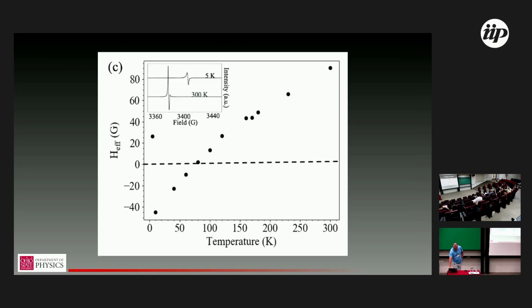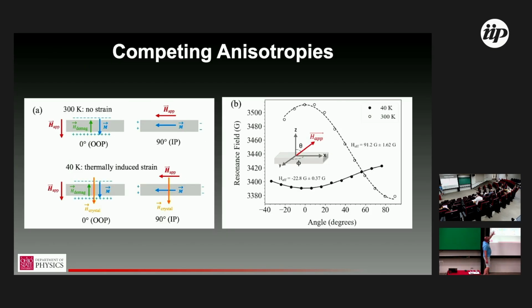And this is, if I understand what you're saying, using the language of sort of g tensor anisotropy, which is sort of the ESR language for talking about the crystal field effects. Yes, that's in fact exactly what I'm talking about here. So the orange arrow is effectively the g anisotropy, the crystal field anisotropy that turns on. And in fact, you'll notice I've very carefully not given you a value for the size of that field, because we only ever measure the sum of these two. So I can tell you the change, but I don't have a good, and happy to take suggestions, but we were not able to think of a way to provide an absolute reference, a fiducial point for the size of that anisotropy field. That's exactly right.